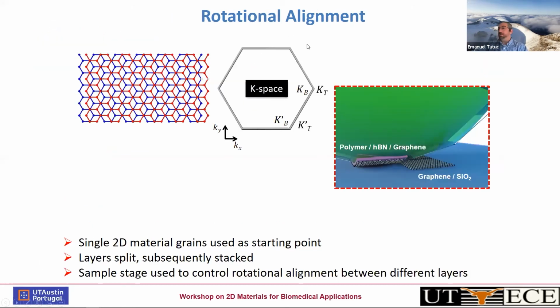But in 2D materials, that's not necessarily a given, and the way we would address it is using something that the community refers to as tear and stack or cut and stack. And this consists of taking a larger grain of a 2D material and splitting it into one or multiple segments and then picking them up sequentially. And if we do that, we would ensure that all these segments would have aligned lattices at the outset, and we can either keep them aligned or twist them controllably if we desire to do so.